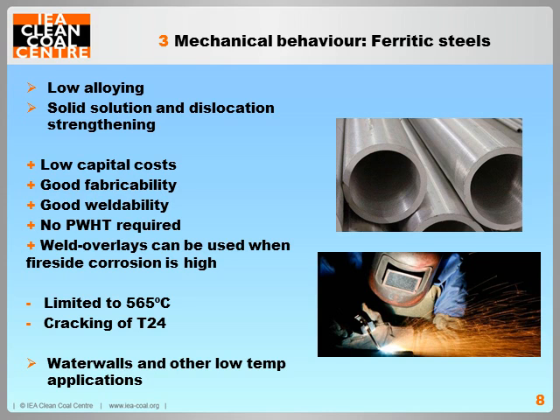So, ferritic steels, they have a low amount of alloying and are strengthened with solid solution strengthening and dislocation strengthening. Ferritic steels are easy to manufacture and they have a good performance all round up to 565 degrees Celsius, where they are then limited by steam side oxidation. They are the only steel that does not require expensive and time-consuming post-weld heat treatment.